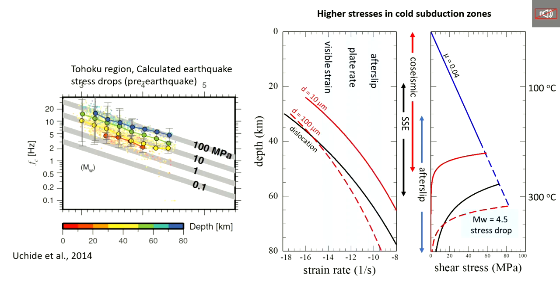And here you see this amazing thing, that the corner frequency-based stress drop increases with depth, up to values of like 100 MPa at 80 kilometers. So now why is that important? It's important for 2 things. One is those estimates are kind of similar to what you predict from this coefficient of friction of 0.04, right? If I extrapolate that down here, this is where the magnitude 4.5 earthquake stress drops are. It's pretty consistent with that. That's pretty cool. But what does that do?